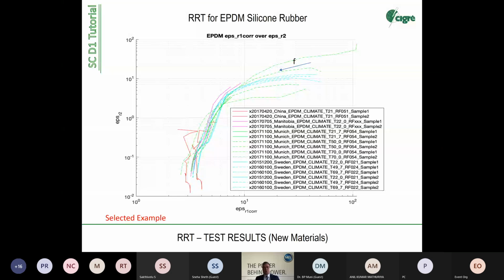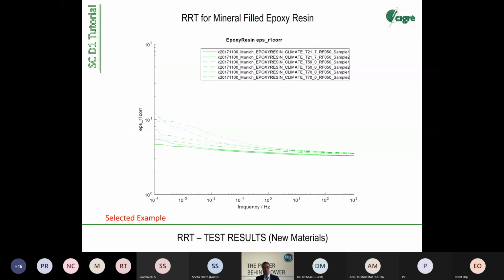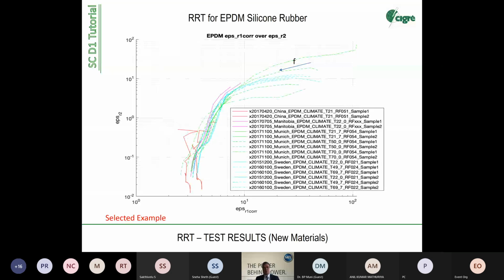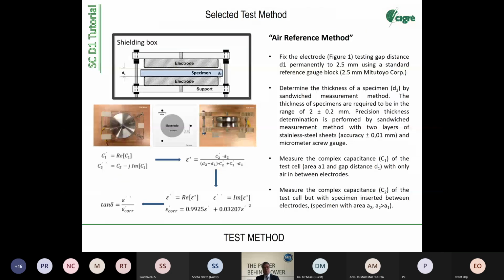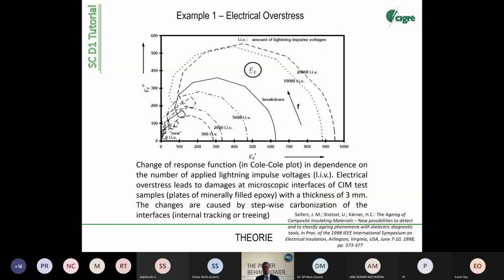Mineral filled epoxy resin. That's what I showed you before. These pictures here. These were same kinds of materials. So you see one material, because of the interfaces, may be susceptible to electrical overstress. And electrical overstress means treeing, means step-by-step carbonization and growth of channels that may lead to failure after time, so aging time. This relates also to the inverse power law.